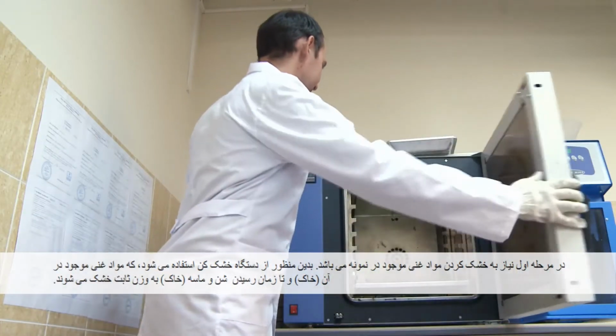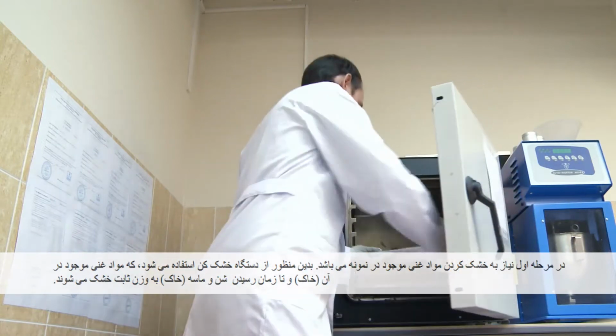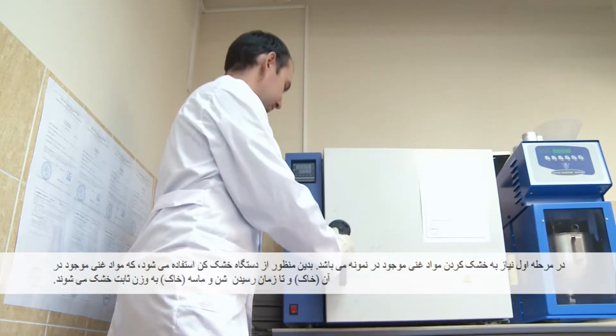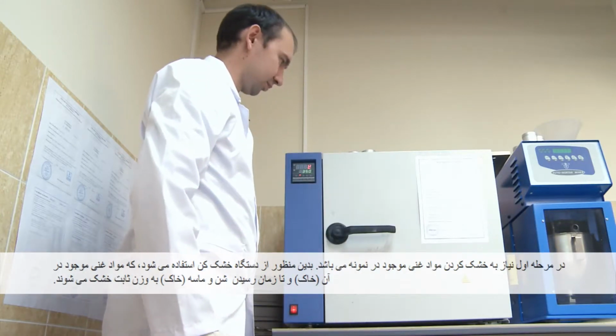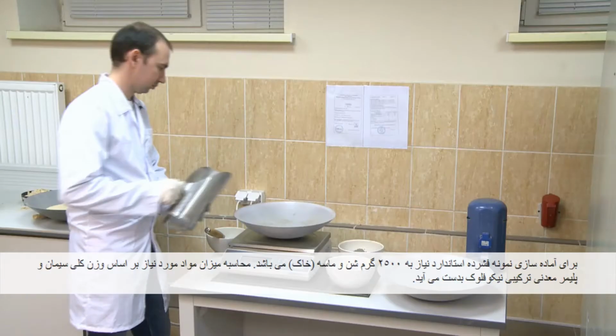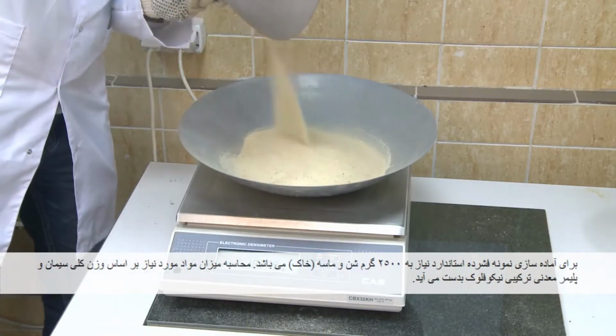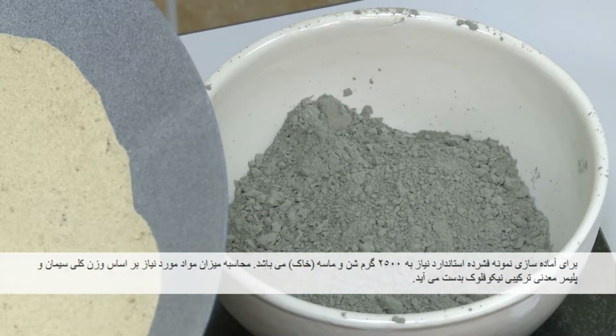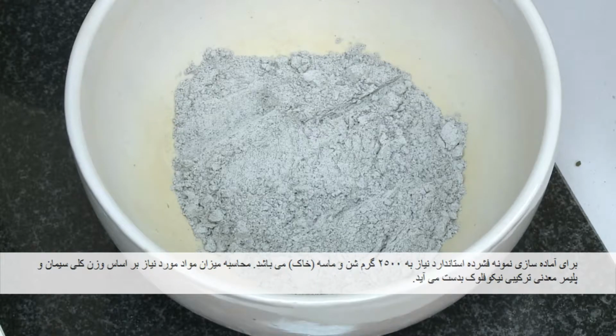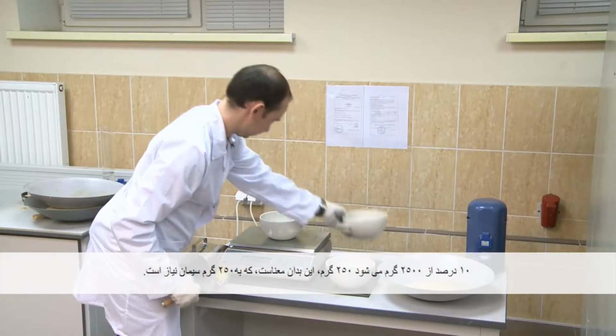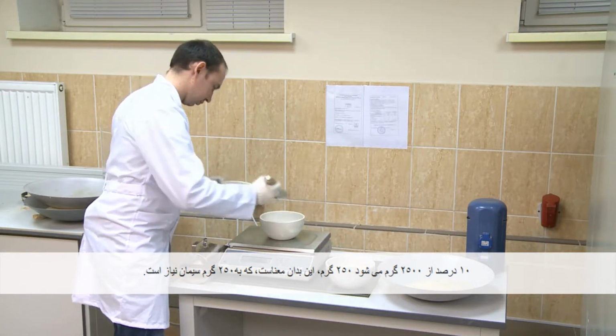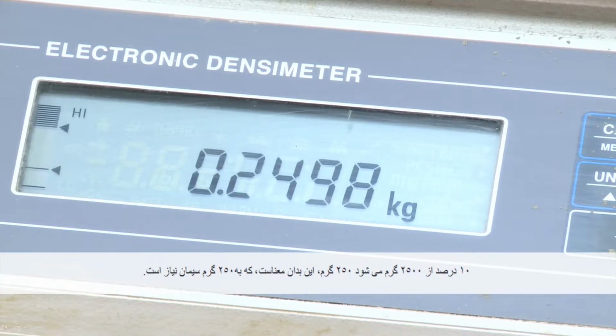For example, let us prepare sand samples improved with 10% cement by soil mass and 1% of mineral polymeric compound Nikoflok by soil mass. First of all, we should dry the improved material. We use a drying cabinet where the improved material, sand in this case, is dried till it reaches constant mass. We need 2,500 grams of dry sand to prepare a sample in the standard compaction measurement device. The amount of cement and mineral polymeric compound Nikoflok is calculated from the mass of filler. 10% of 2,500 grams equals 250 grams.